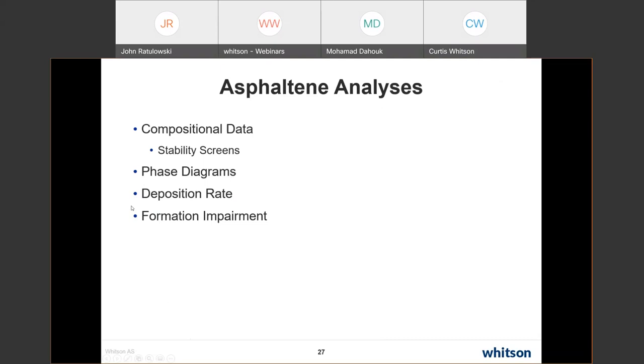You can try to measure deposition rate, but this is even harder than it was in wax. Mostly because a lot of this occurs at high pressure and high temperature, which is difficult to do in something like a flow loop. Formation impairment also is a very, very difficult measurement. And it's one that we've worked on a bit, and I'll share some of the results of that with you as well.